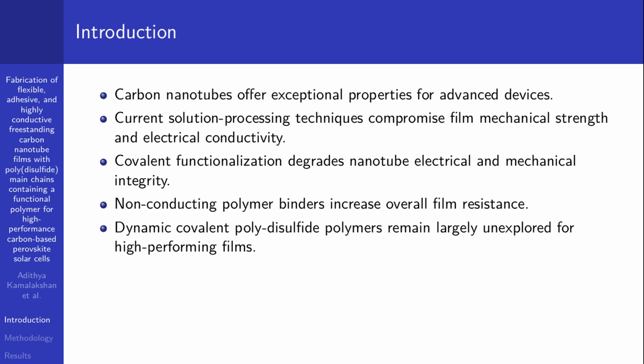Furthermore, covalent functionalization, a common strategy to improve dispersion, unfortunately introduces defects that degrade the nanotube's inherent electrical and mechanical integrity. Non-conducting polymer binders, while providing structural support, typically increase overall film resistance, limiting performance. Crucially, the potential of dynamic covalent polydisulfide main chain polymers, especially those with functional carboxyl side chains, has been largely unexplored in creating high-performing carbon nanotube films.